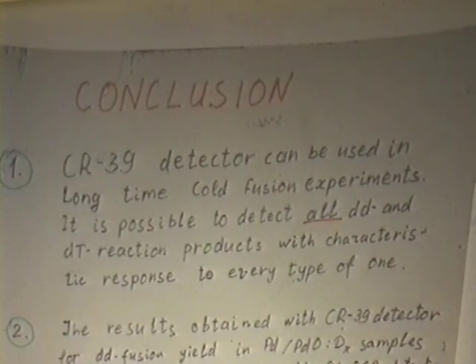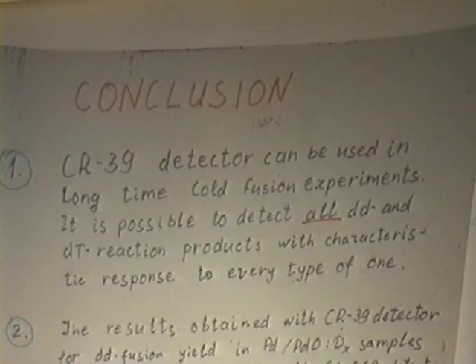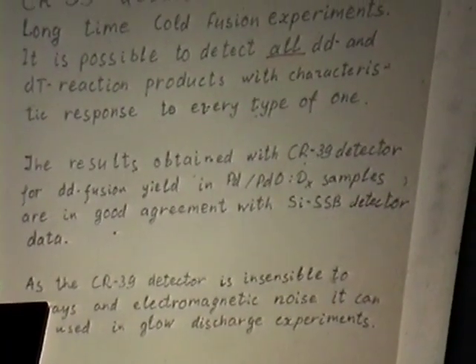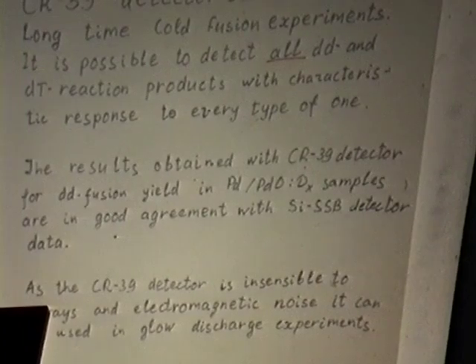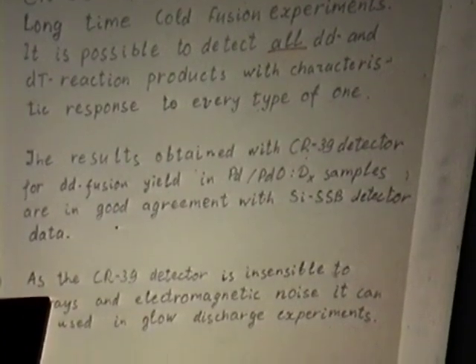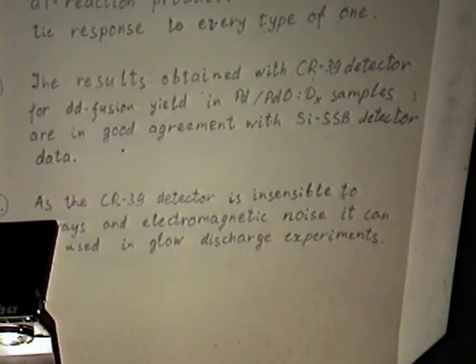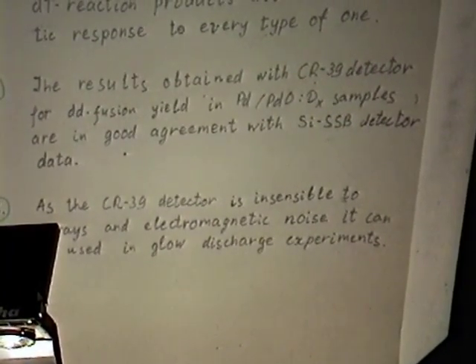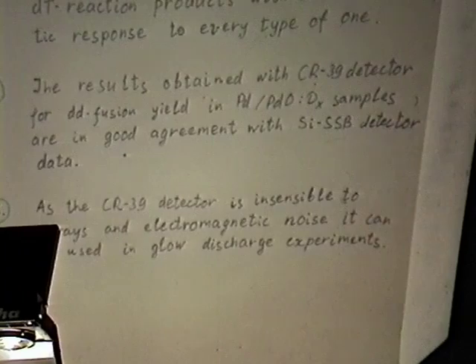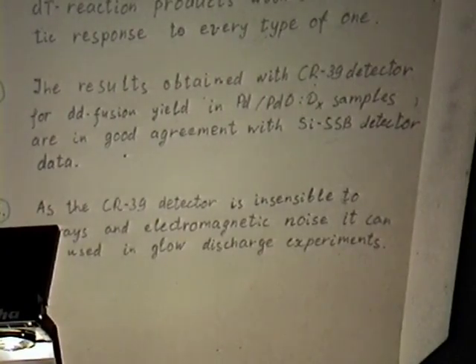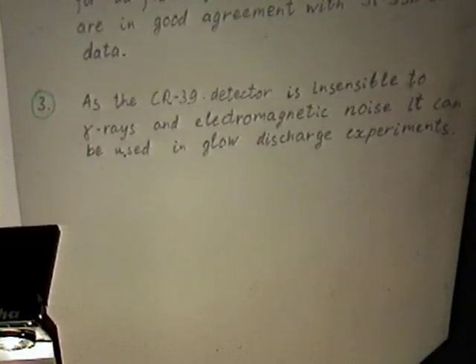Second point, the results obtained with the CR-39 detector for the deuterium yield in palladium oxide deuterated sample are in good agreement with silicon surface barrier detector data. As the CR-39 detector is insensitive to gamma rays and electromagnetic noise, it can be used in glow discharge experiments. This is the final point.